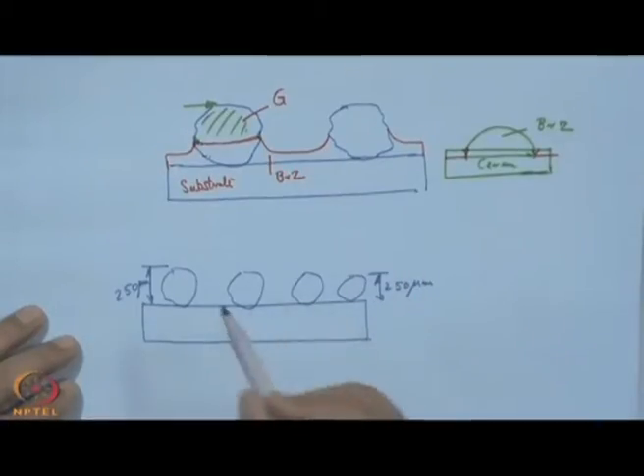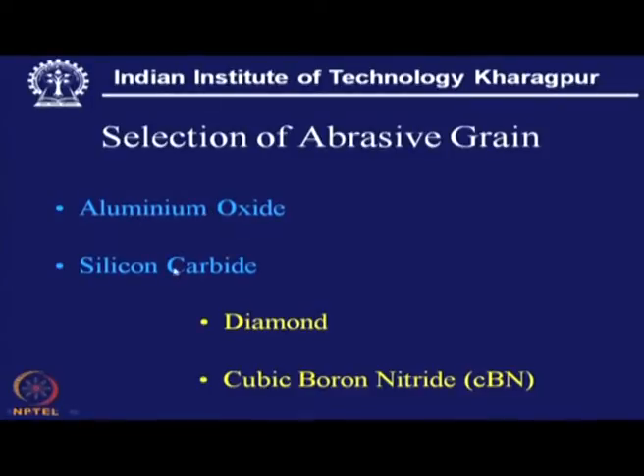Considering this one layer arrangement, it is obvious that the grit material with higher grinding ratio should be the obvious choice. That is why aluminum oxide or silicon carbide are not the first choice; rather, diamond and cubic boron nitride, that means CBN, are the materials of choice for this single layer configuration.